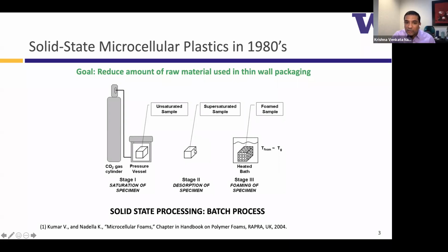And this thermodynamic instability that comes from supersaturation, if you simply provide it energy by heating it in a hot water bath, somewhere close to 90 centigrade, you will see that the volume of the plastic expands because there are billions of small bubbles that are created. Typically in the thermoplastics that we work with in Professor Kumar's lab, we can control anywhere between 100 million to 1 trillion bubbles per cubic centimeter. And typically the temperature in this heated bath is somewhere close to the glass transition temperature of the thermoplastic material. So as you can see, it's a batch process.